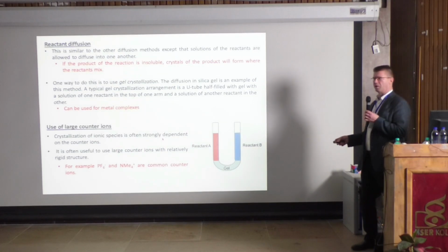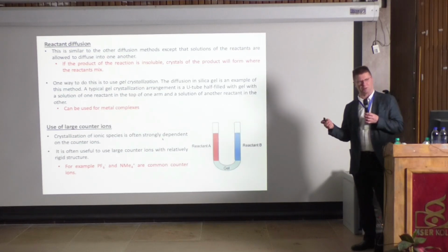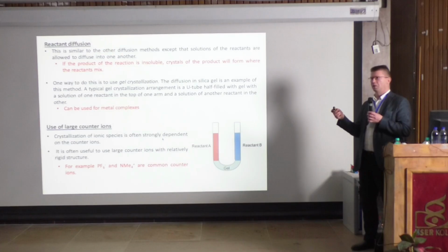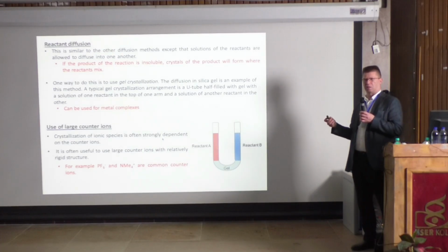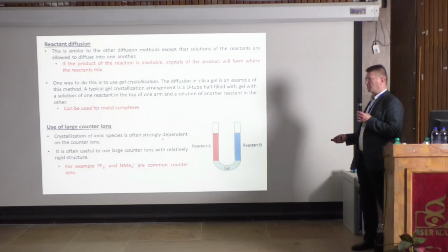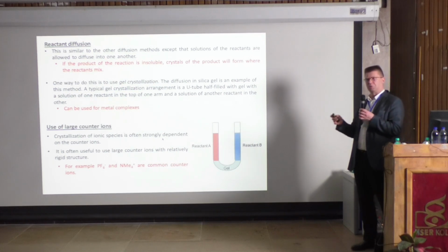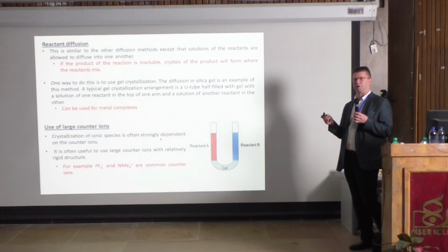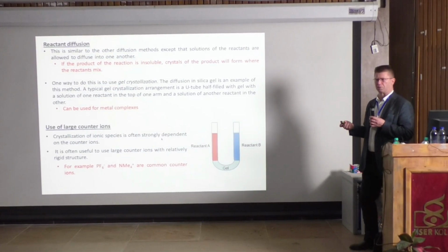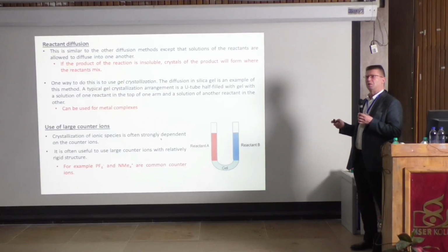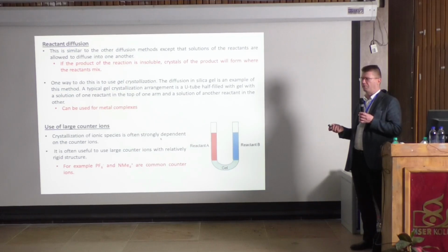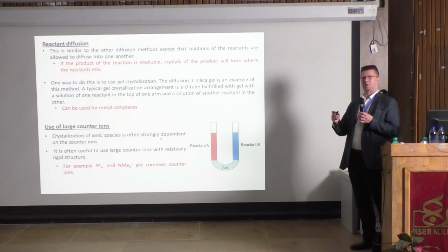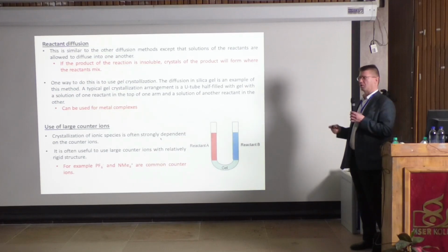And then if you have an anionic system and you want to crystallize it, when you use alkali or any metal cation, it will coordinate to your anion in the solid state, and that's a bad thing. So then you use non-coordinating cations like TMA. So there are really big modulation possibilities when you are working with non-molecular systems, so charged systems. An ionic system is like a molecule, because it has a positive and negative charge in itself, but it can also help sometimes that the charges will interact and then it will create a nice crystal.